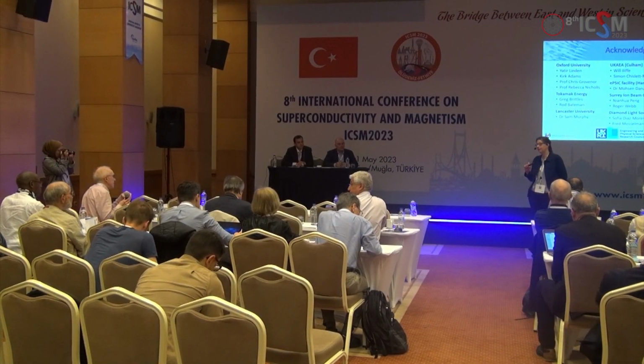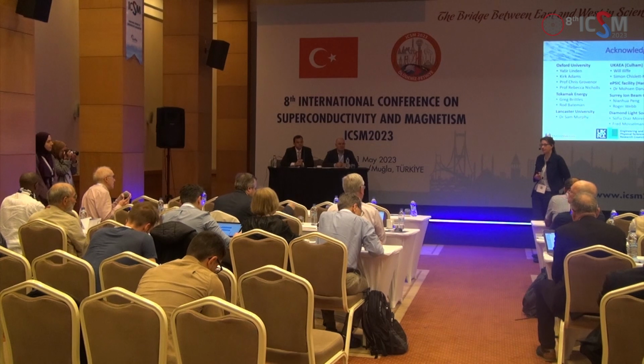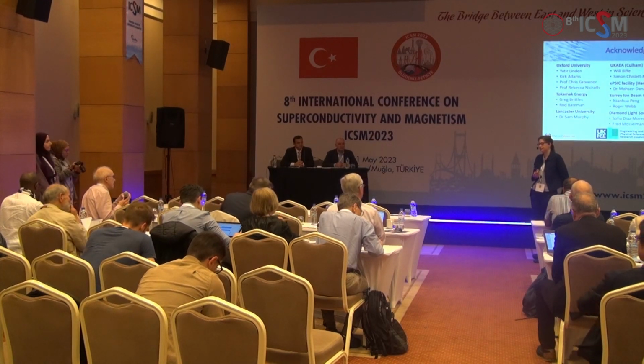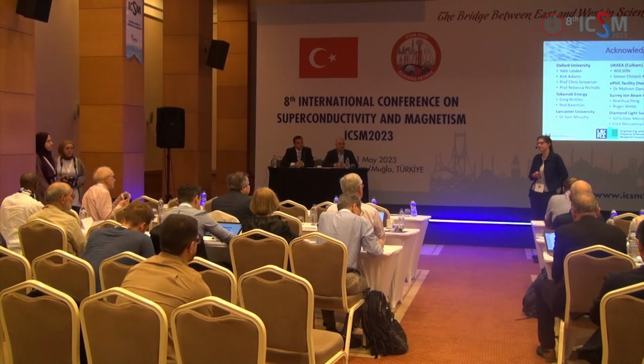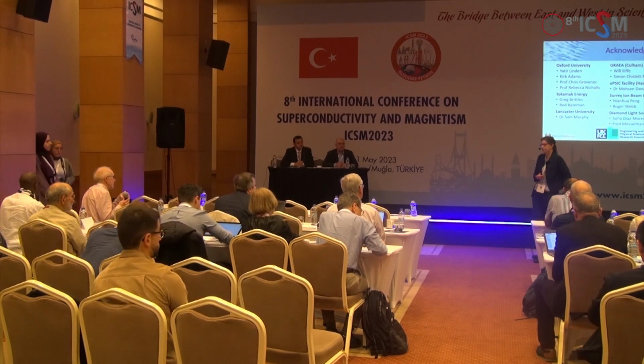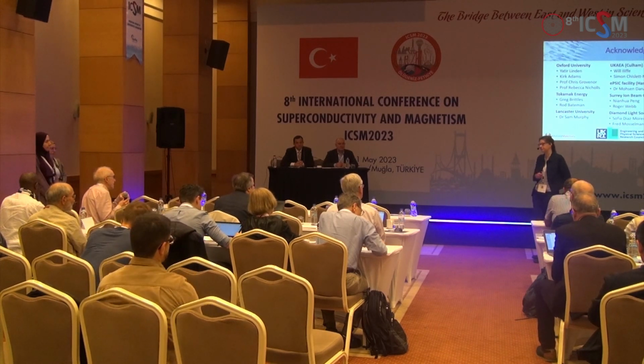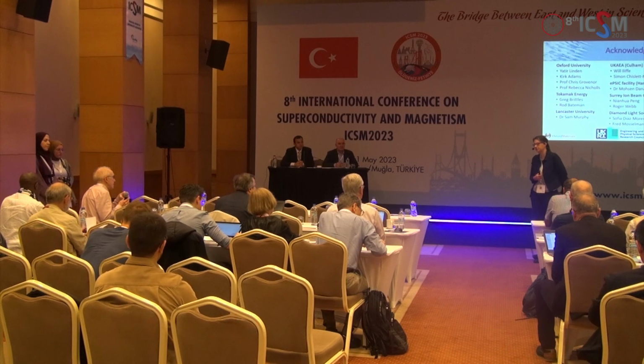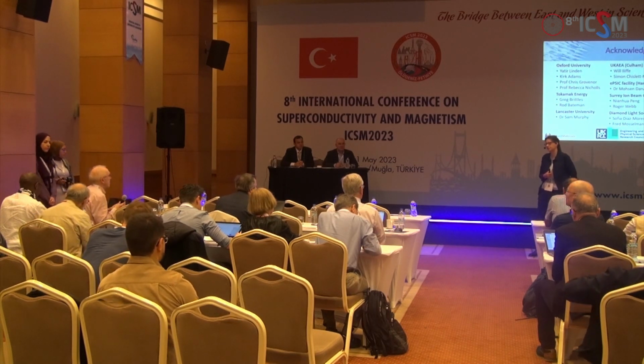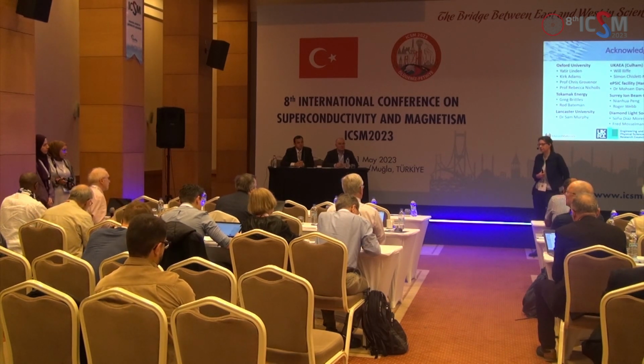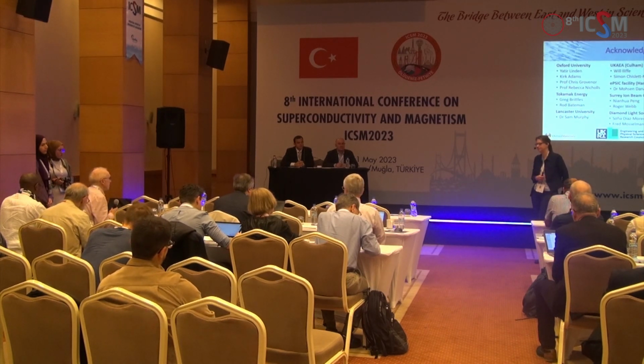Certainly, Michael can tell you more, but certainly with the fission spectrum neutrons, they've got to be very careful with the thermal neutrons that are produced as well, because particularly with gadolinium, there are particular reactions that happen that are much more damaging with those thermal neutrons. So they shield those out if they want to look at the effects of the fast neutrons using fission spectrum. But there is no high enough flux source of fusion neutrons to do the experiments, so nobody's done them.